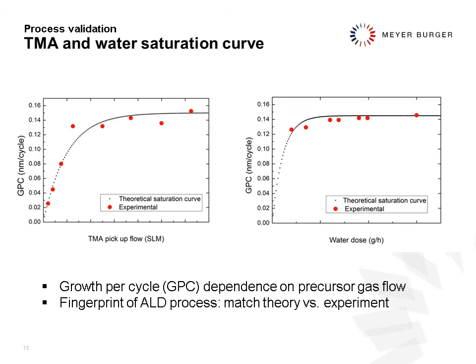So what do we look at when we have aluminum oxide? We look at the growth per cycle. Why do we look here? Because, as we said, this is a certain reaction that needs to take place, and it takes place during a cycle. So what you can expect is that what you do in a cycle is always the same. It's just that what we are playing with is how quickly we can switch between cycles.